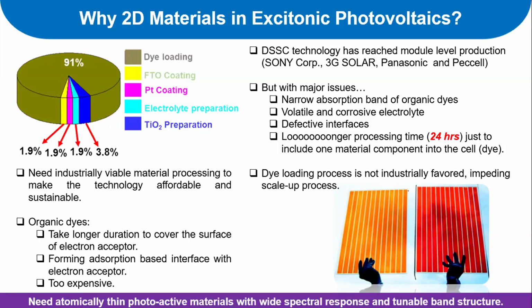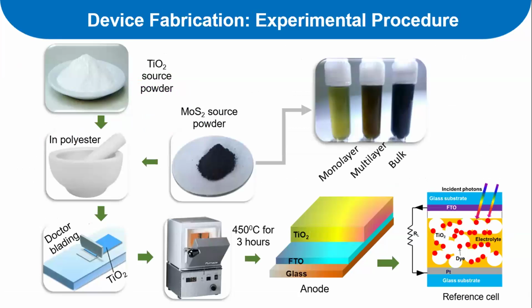We need 24 hours to load the photoactive material onto the electron acceptor. A minimum of 24 hours means industrially it is not a viable process, so they don't like it. Due to this kind of reason, the major problems with quantum dot or dye-sensitized solar cells exist. So we need some potential candidate to replace these organic dye molecules or quantum dot materials, and they need to be extremely thin so that they can be coated on other electron acceptors, just like the way that we coat quantum dots and organic dyes on titanium dioxide or zinc oxide or any other metal oxides, and that can be used in excitonic photovoltaic technology.